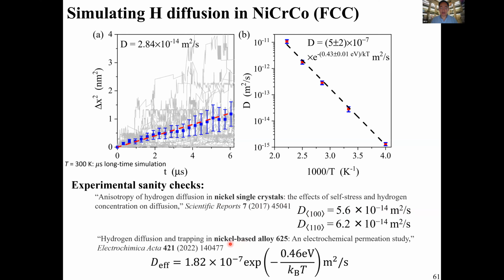And then there is another nickel-based alloy, 625, which is also a polycrystal. And they have a prefactor, which is 1.8 times 10 to the minus 7 meters squared per second. We have a prefactor, which is like double that. And then it has an effective activation energy of 0.46 eV. For this complex alloy, we are 0.43. So this is not really conveying really accurate information because these are alloys and this is not the same composition, but it's just to say it seems to be able to produce something that could be the same.